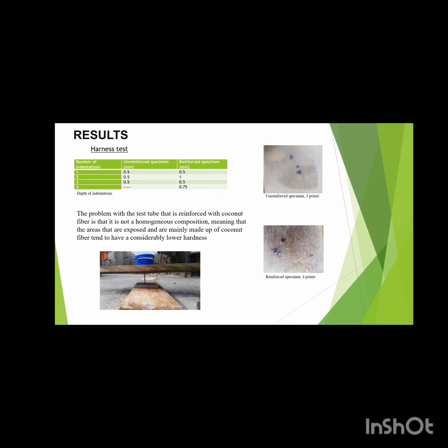Then we have the hardness test. Considering the data shown in the table, it is considered that the hardness obtained by the resin without any reinforcement is higher because it is constant and prevents the indenter from leaving a greater mark on the material. The problem with the test tube that is reinforced with coconut fiber is that it has a non-homogeneous composition, meaning that areas that are exposed and are mainly made up of coconut fiber tend to have a considerably lower hardness.